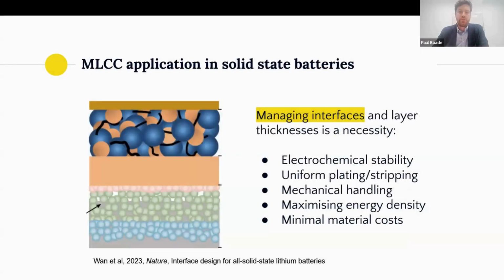Absolutely, a great question. It's a pre-metered process. So volume flow and web speed determines your thickness, just like with slot. We went all the way down to 30 meters per minute with dry film thicknesses of around 100 to 150 microns. And at the upper end, the 350 meters per minute speeds for the silicon anodes were dry thicknesses of 20 microns. Okay. So that gives you a range expectation.